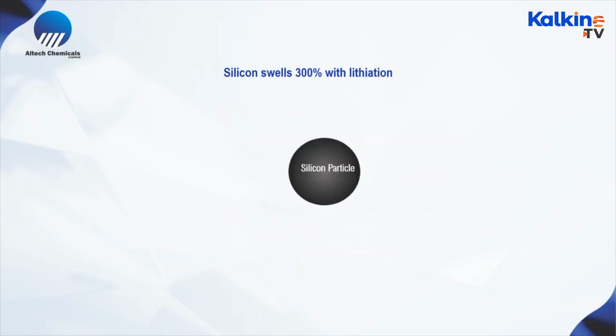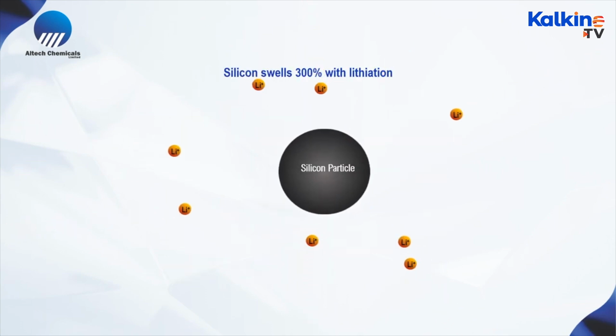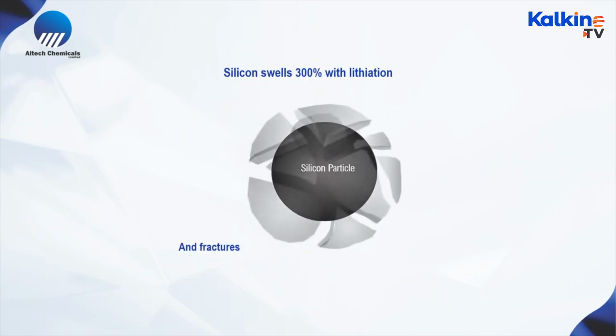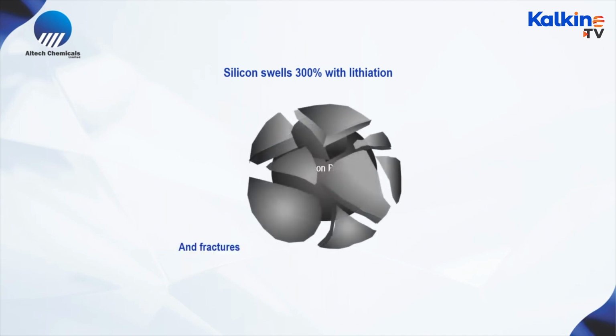Now, if silicon is such a promising anode material, why isn't it being used in lithium-ion batteries today? Essentially, there are three problems, Rachel. The first problem is that in a lithium battery, silicon expands 300% in volume to the point that it fractures. Number two, it has that SEI layer, or the first cycle loss. Instead of 10% for graphite, it's probably close to 50% for silicon. So imagine 50% of your lithium inventory is absorbed on its first charge. And then thirdly, it's got a very high fade, so the performance of the battery drops if you don't resolve the three problems of silicon.